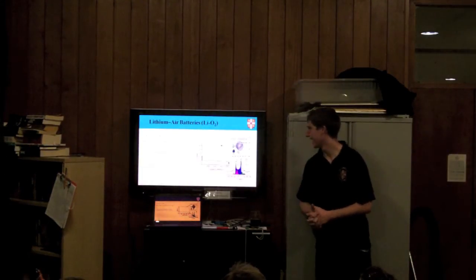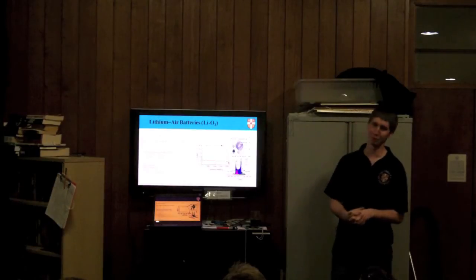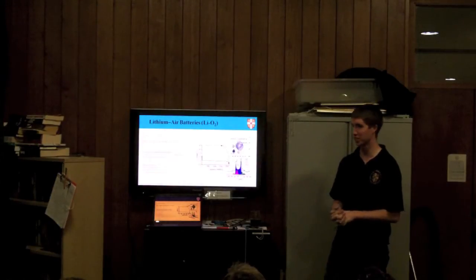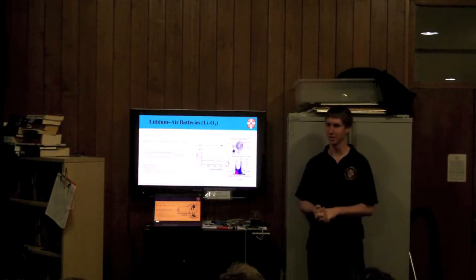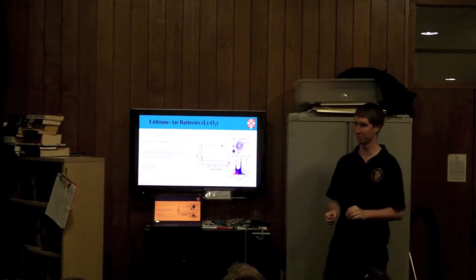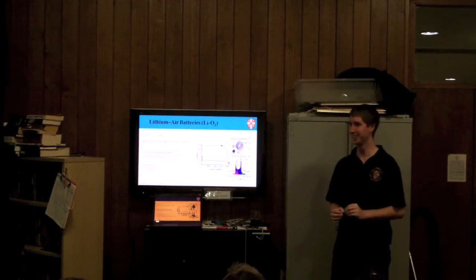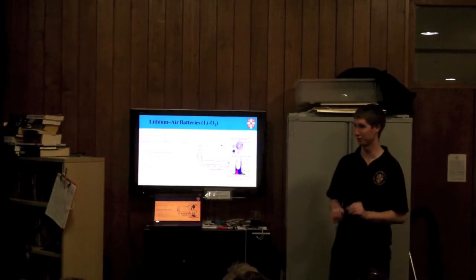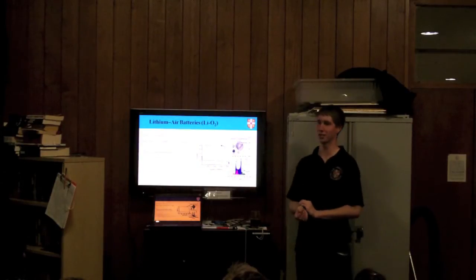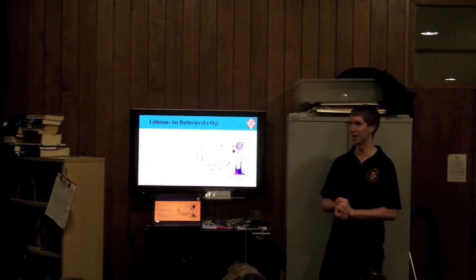There are some pretty massive problems with Lithium-air, one of which is that Lithium-air is a misnomer. This is lithium ultra pure oxygen, not air. If you put air in this, it won't work for 1 cycle. If you put ultra pure oxygen in, it will work for a few.